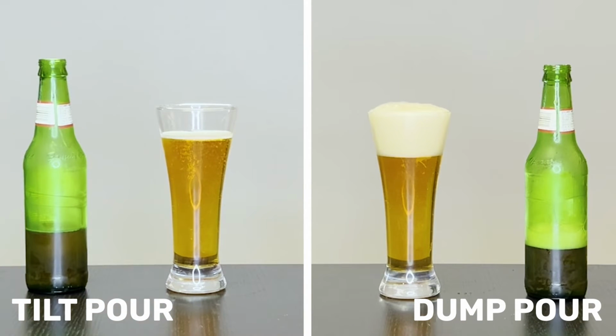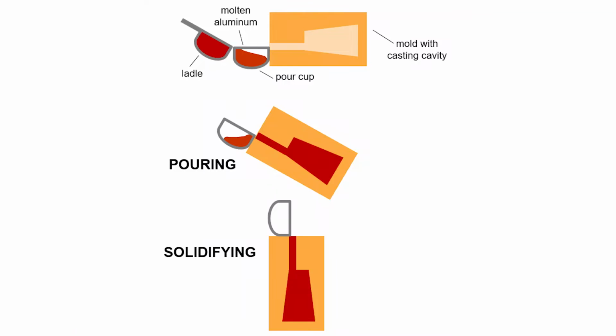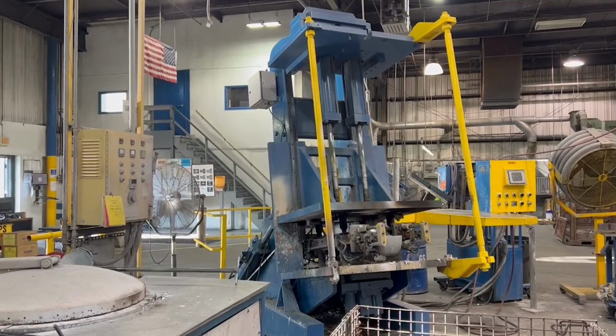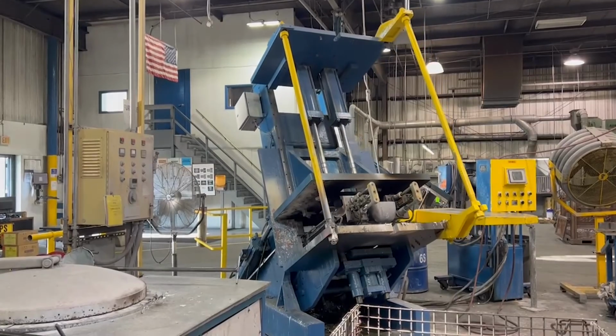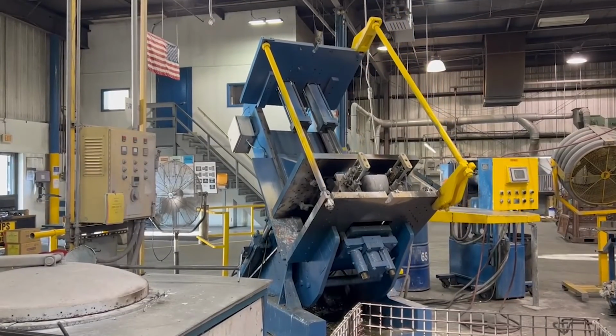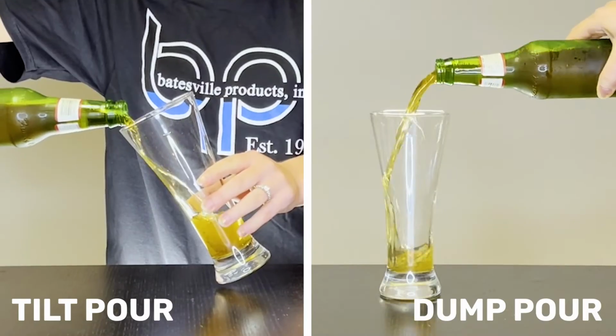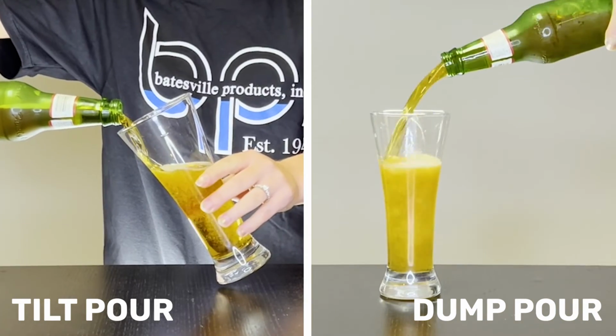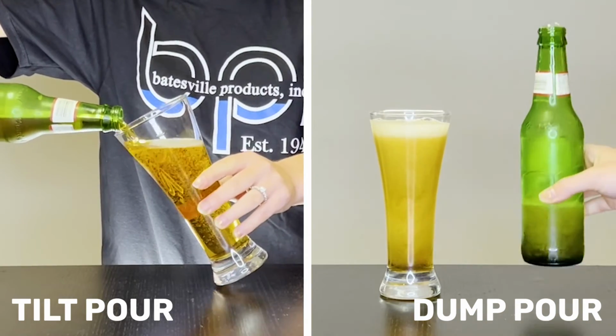In permanent mold casting, we prefer the tilt pour process. So in the tilt pour process, the mold is mounted to this tilting machine. You pour the metal into a pour cup, and then the machine tilts back at a controlled rate. This lets gravity gradually feed the metal into the cavity at a tilt. So it's gradually running down the sides instead of just splashing into the bottom of the mold.